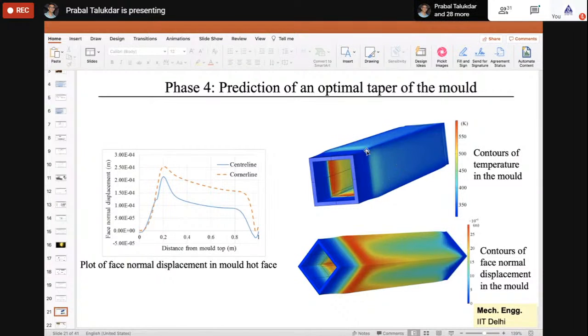From these temperature distributions, using the mechanical model, we have calculated the displacement in the mold. If you see the displacement contour, the displacements are higher at the top of the mold, close to the meniscus, and gradually decrease. But of course the displacements are very small, something to the power of minus 5. So the deformation of the mold is not very large, as we might think. Mold deformation is very small compared to the deformation of the billet, although whatever millimeter or micrometer deformations we have are also important for an accurate model.